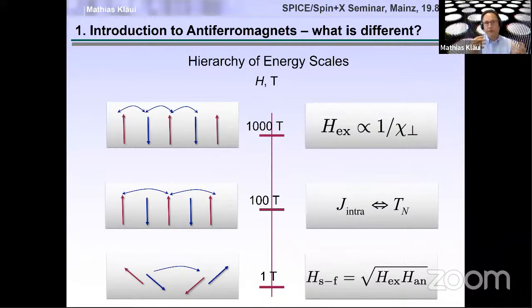The big difference is that the two sublattices are different materials. So gadolinium iron at the compensation point just has the same moment for gadolinium as iron, but the two sublattices are not identical. So that makes it different. However, if you look, for instance, at the magnon spectrum, you can, at the compensation point, get similar magnon spectra as you have for